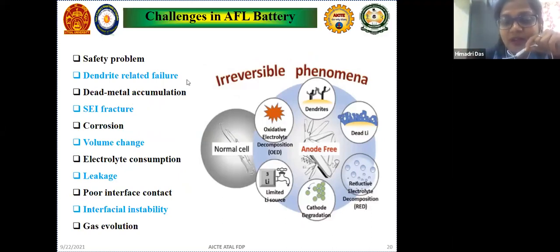These effects start after a few cycles of charge and discharge. After a few cycles, the current collector where we are using copper is not only copper, because lithium will be deposited on this layer, and that same thing will start the dendrite growth. And the lithium source will generate dead lithium. So there will be a very insufficient amount of lithium, which will ultimately reduce our coulombic